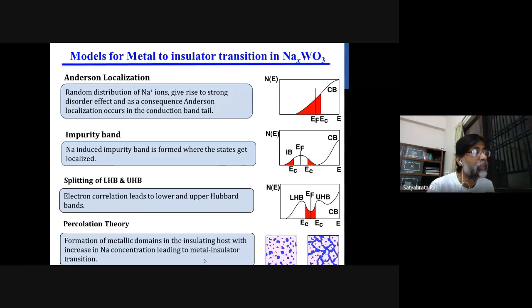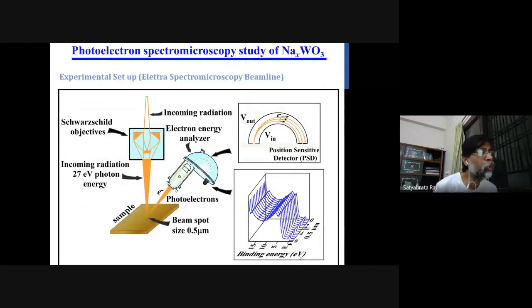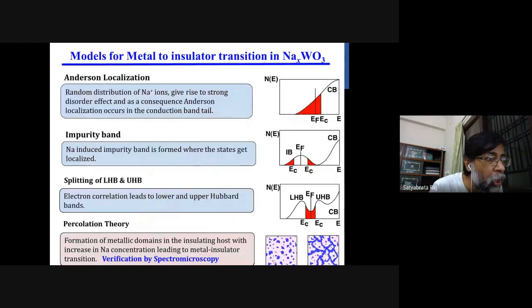So let's first validate whether this percolation theory is right or wrong in the context of sodium tungsten bronze. Then you have to do a special type of spectromicroscopy experiment. What does it mean? You can do photoemission spectroscopy, collect spectra, and see that as a microscopy, and your spot size has to be sub-micron. That means if the spot is falling on this pink region, it will give you an insulating feature, whereas if the spot is falling on this blue, that will give a metallic feature. That way, you can say that inhomogeneity is there inside the sample, and the percolation theory can well explain your metal-insulator transition.